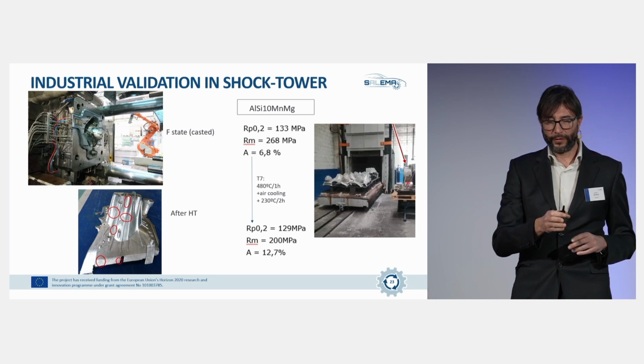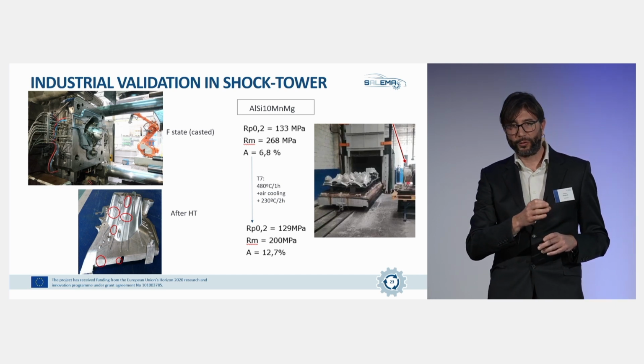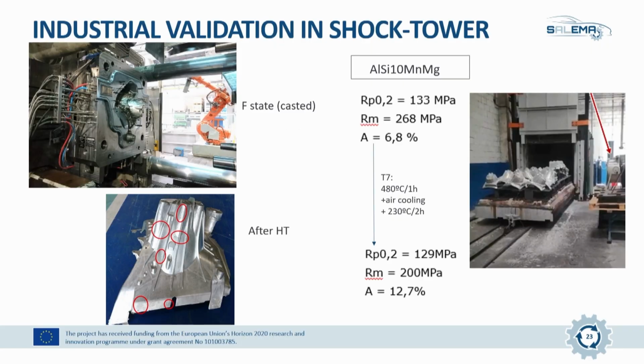And here you have the mechanical properties in the cast condition, and after a T7 heat treatment of 1 hour at 480 degrees C, and then artificial aging of 2 hours at 230. Okay, and the mechanical requirements of the shock tower were met. That is 120 megapascal for yield strength, 180 for ultimate tensile strength, and 10% of elongation.